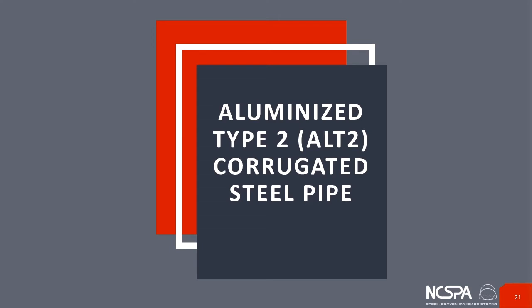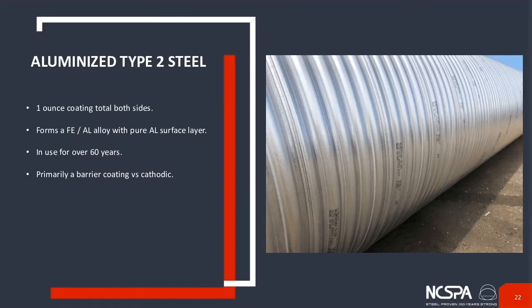So changing over from galvanized to aluminized steel, you're going to see some pictures and you're not going to be able to tell galvanized from aluminized steel. But once you become familiar with it and you see it in the field, you can see it is a different finish, a different color. And it is a completely different approach from galvanizing. Galvanizing, we talked about, was a cathodic protection system. And while there is some cathodic protection offered by the aluminum on the steel, its primary function is as a barrier coating. It's a barrier coating versus a cathodic protection. It's a 1-ounce coating. We'll talk about how that's applied in a minute. It's a very unique product that comes out.